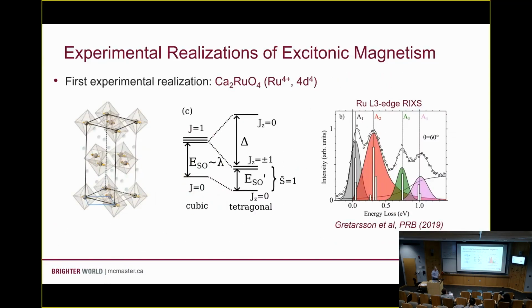So people went away from this large spin orbit regime to the 4d transition metals, okay? Going down to a smaller spin orbit energy scale. If you have less spin orbit coupling, it reduces the size of this gap, makes it easier to close the gap to condense this effective J=1 state. Okay? And the first experimental realization of this excitonic magnetism was ruthenate, calcium ruthenate 214.